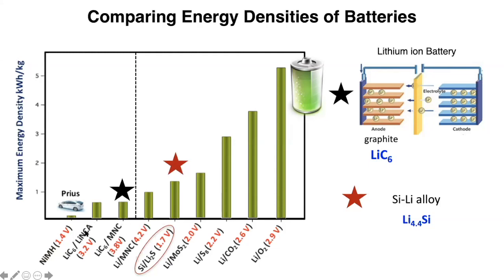So with the known cathode material, these are mostly based on inorganic lithium compounds. Then the energy density is marked here, and you can see that the energy density is still relatively low. Then if we look at the choices of other materials, you see mostly it's lithium. But then before the additional lithium as anode, you can see, oh, here there's silicon. Silicon is abundant, and if I remember correctly, it's the second most abundant element on the earth. So if this can work as an electrode for lithium ion battery, then that will be really economical. And also look at the energy density, it's much higher compared to that of graphite as the anode.